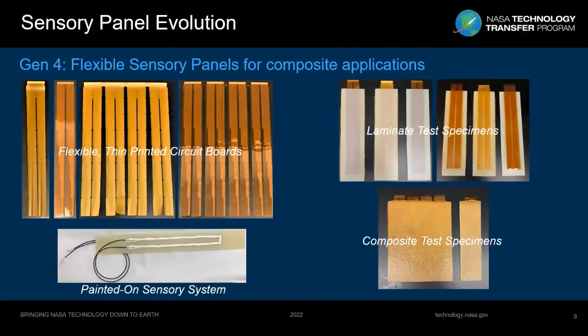And so now we're getting to some of the more recent work, which was our Gen 4 system, and this is the most current system. And we decided to focus on the ability to embed our sensory system into composites. And so to do so, we decided we were going to use flexible thin printed circuit boards and embed these into the composite structures and use these flexible circuit boards as a monitoring system, much like what you had seen in the other systems. And so the image on the left shows panels, or what we call the 2-finger and the 4 or 8-fingered sensory panels from 2 different vendors.